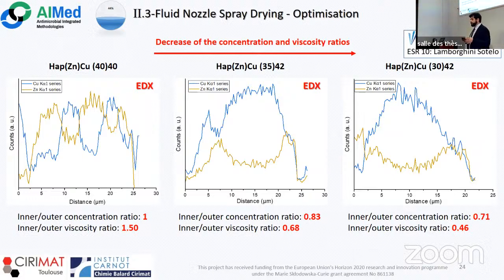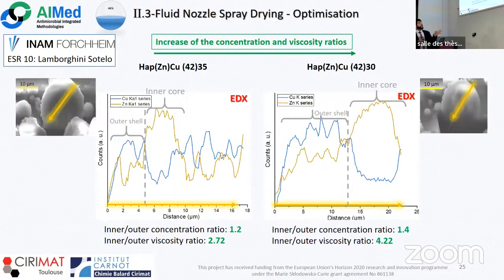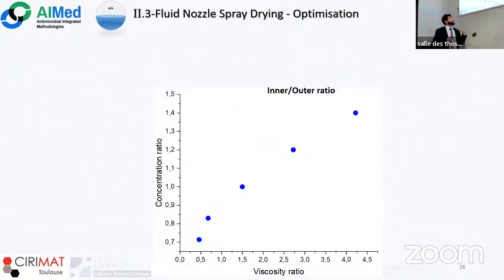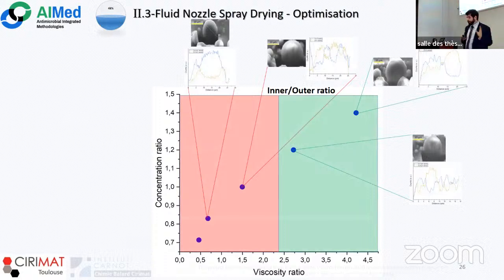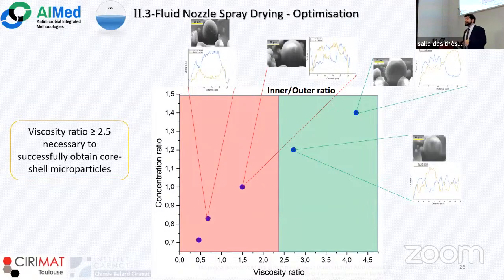And we can observe at first, after focused ion beam milling, the EDX analysis of these particles. As you can see, by decreasing the concentration and the viscosity ratios from 1 and 1.5 to lower than 1, we never have a proper core shell structure. On the other hand, by increasing the concentration and the viscosity ratio up to 4.22, we have a segregation of the copper on the outside and the zinc on the inside. So, as a conclusion, we can obtain different core shell structures. We can optimize this kind of core shell structure by assessing that, for our conditions and for our system, a ratio between the inner and the outer viscosity of at least 2.5 is necessary to get these proper structures.